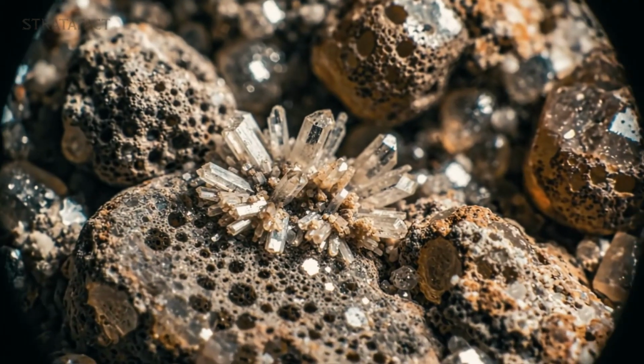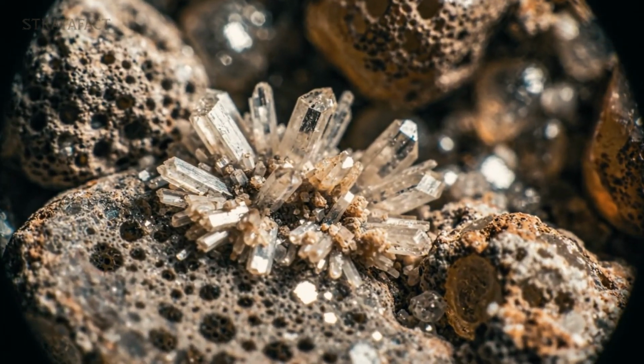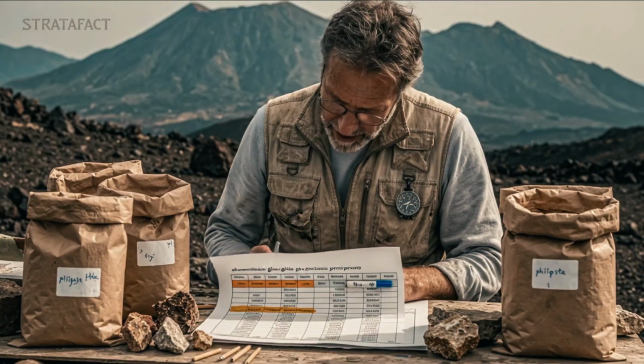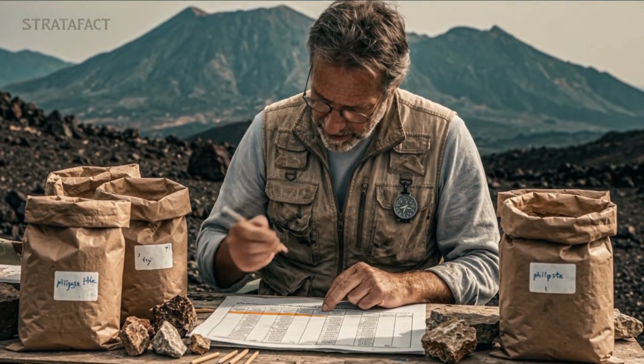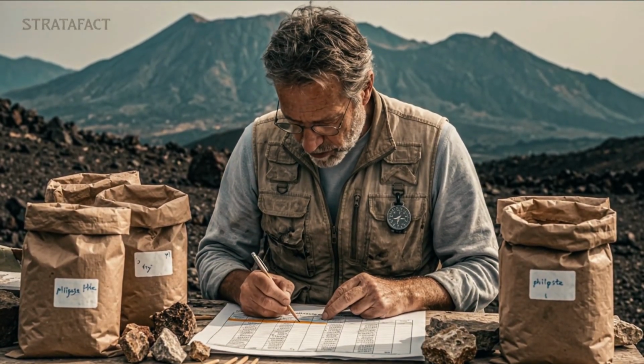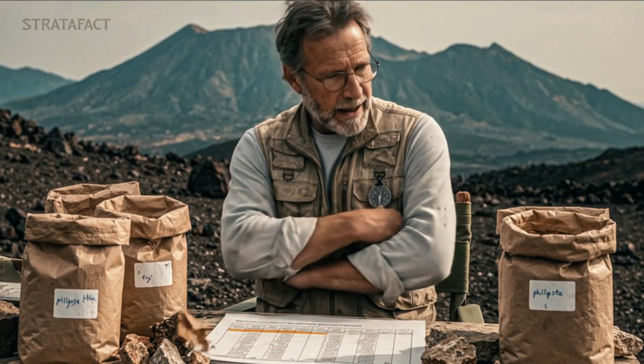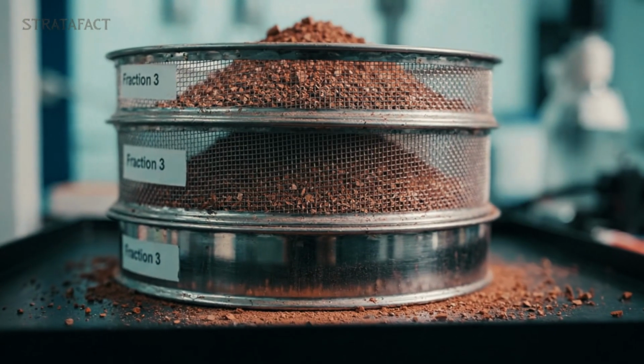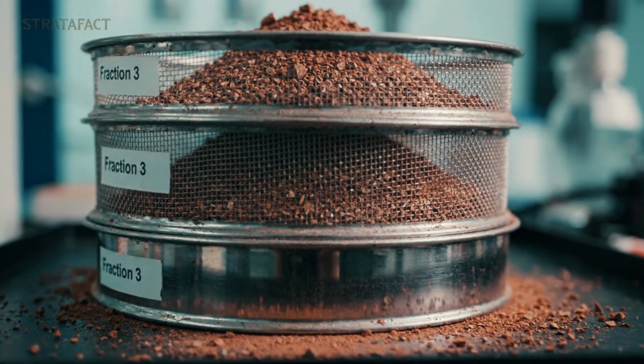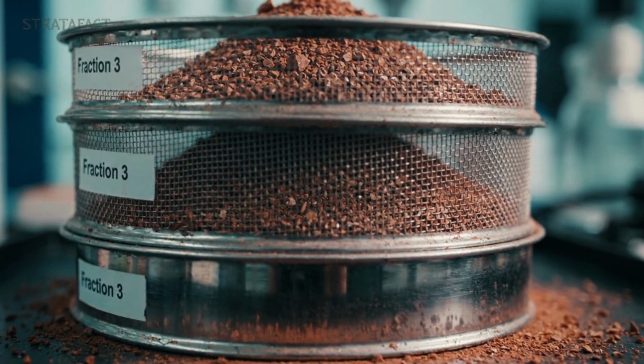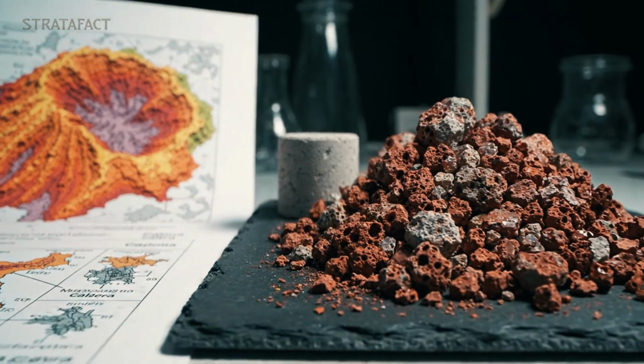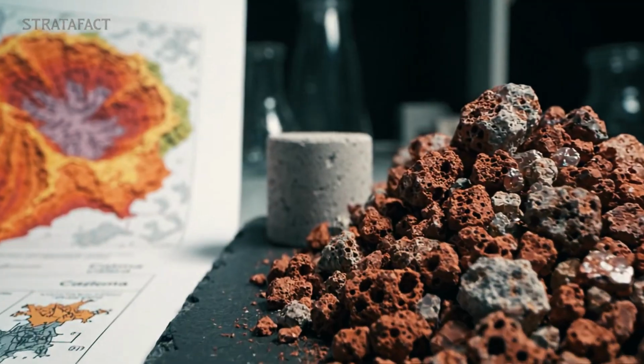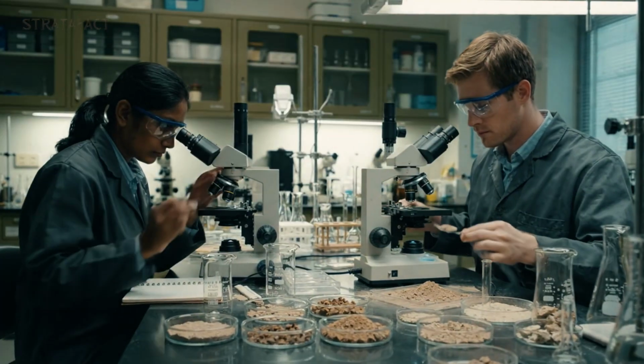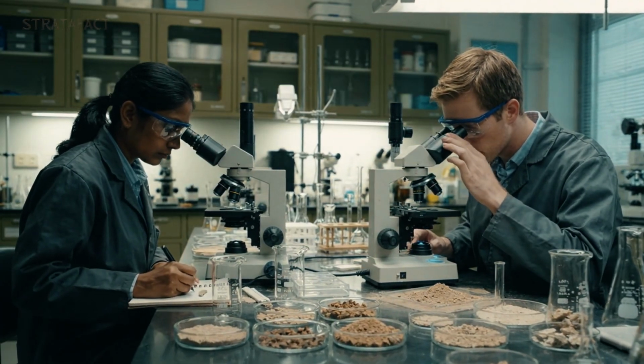The aluminosilicate glass content, the proportion of reactive minerals like philipsite, and the particle size distribution all affect the pozzolanic reaction rate and the conditions under which tobermorite nucleation can occur. Campi Flegrei ash is unusually high in reactive aluminosilicate glass compared to most volcanic ash deposits, a function of the specific magma composition of that caldera system.